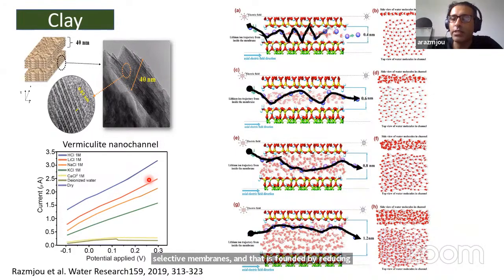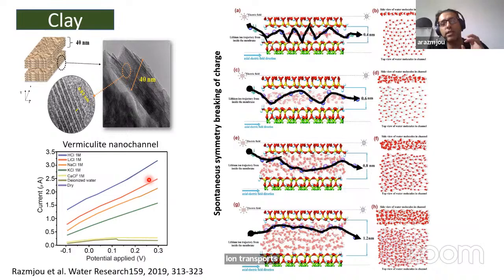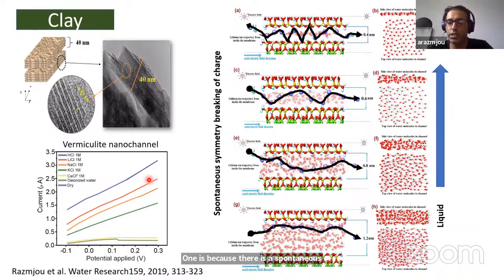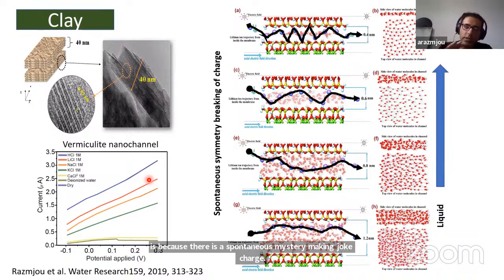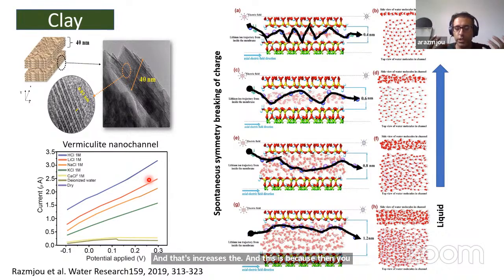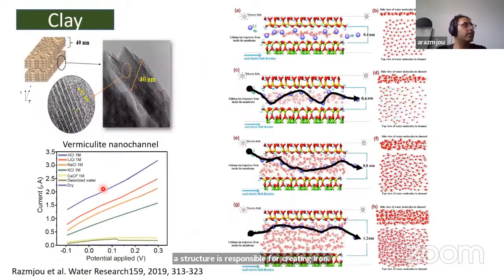The main reason for that is a spontaneous symmetry breakage of charge. This is because when you reduce the nanochannel size, the water molecules form a sort of ice-like structure, and that ice-like structure is responsible for creating lithium ion selectivity. The other thing is that